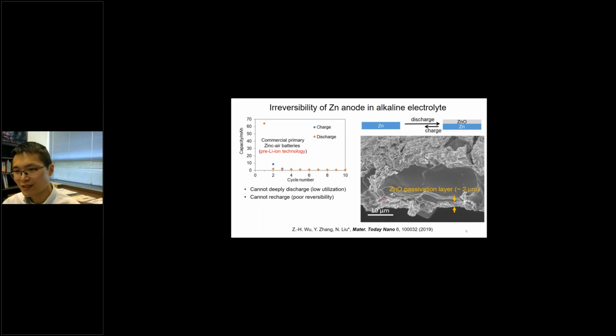And we even did an experiment. We fully discharged a piece of zinc and opened the battery to look at the cross section. You can see there is a lot of zinc metal still inside, but it cannot react because the outside is covered by zinc oxide. And it's only about 2 micrometers thick, and that's enough to passivate the fresh zinc inside from further reaction. So that's the problem.